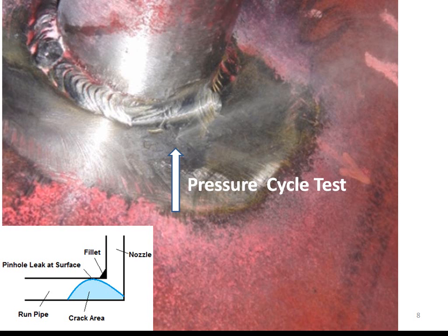This is a pinhole leak that occurred during a pressure cycle test. The run is a 20-inch by half-inch wall pipe, and the nozzle is a 2-inch Schedule 40 pipe. The crack area occurs in the longitudinal direction of the pipe, as we might expect. You can see from this figure what the crack area looks like and why we see only a pinhole leak at the surface. Here's some additional close-ups of the pinhole leak and the excavation that followed the crack from the surface to the ID of the pipe.